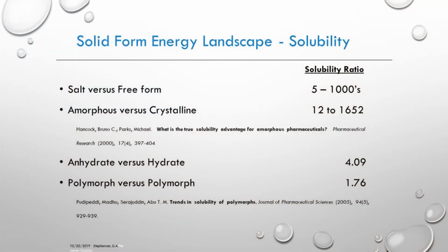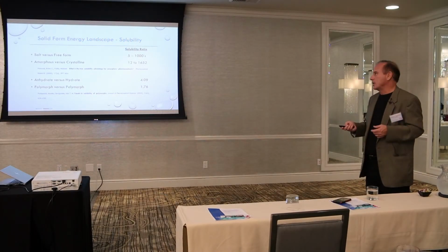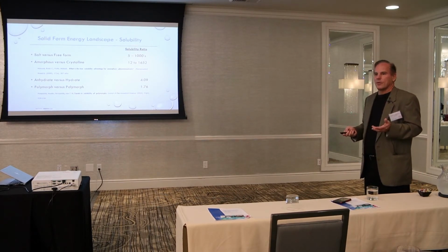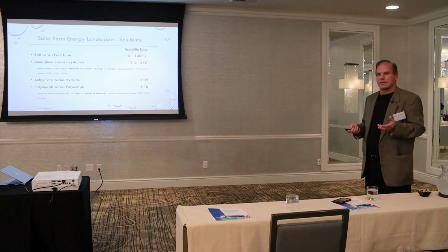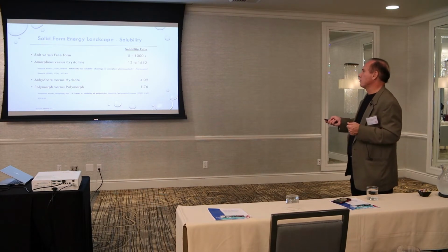Part of the importance of the salt is that it is the most traditional means of improving the bioavailability of a compound, if you have one that's in the BCS class 2 or one that's poorly soluble and you think that it might have to be a relatively high dose. That is salt formation. This is why salt versus free forms is established very early on, and the solubility ratio of a salt form can be as much as 1,000 times more soluble than, say, the free or the neutral form of the molecule.